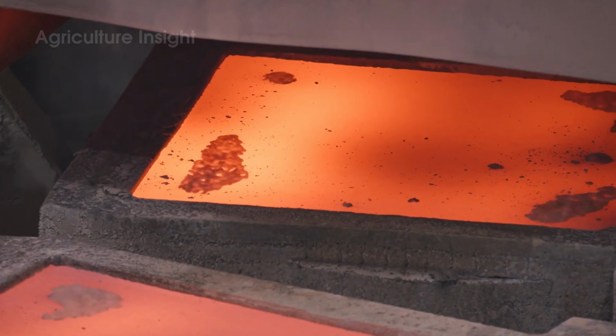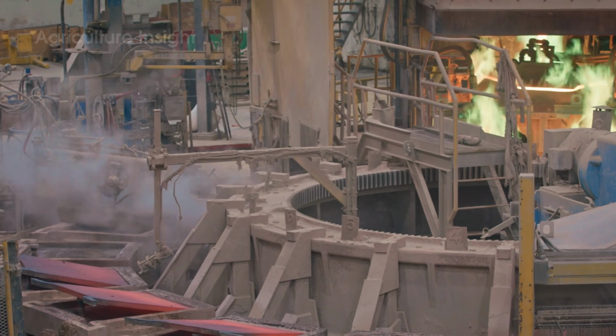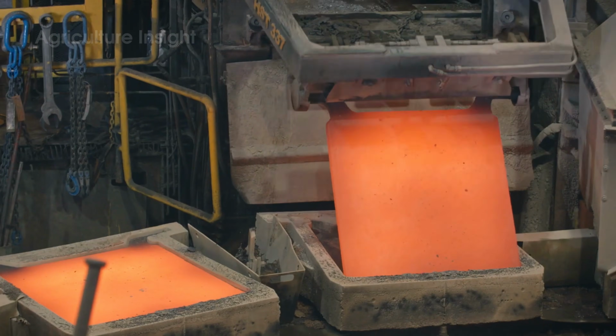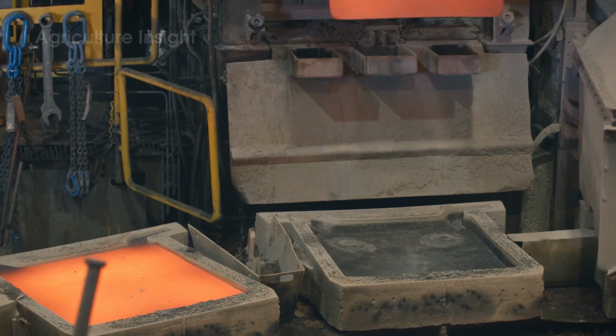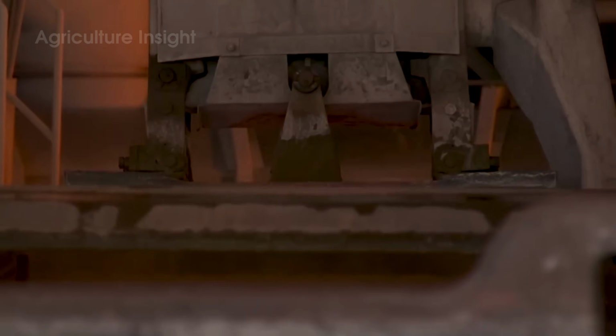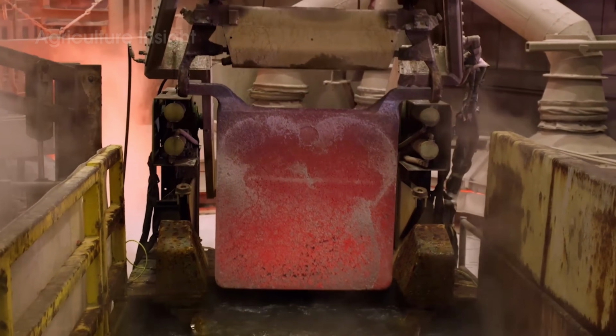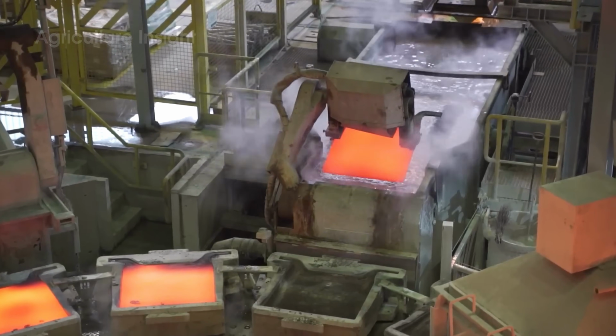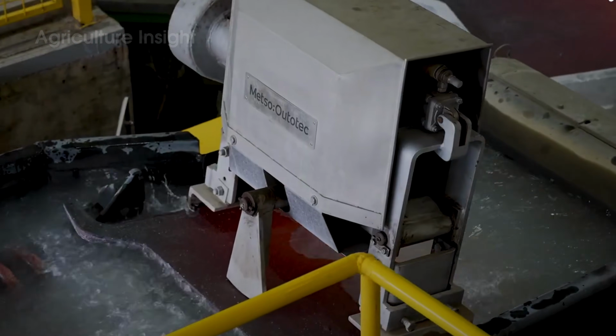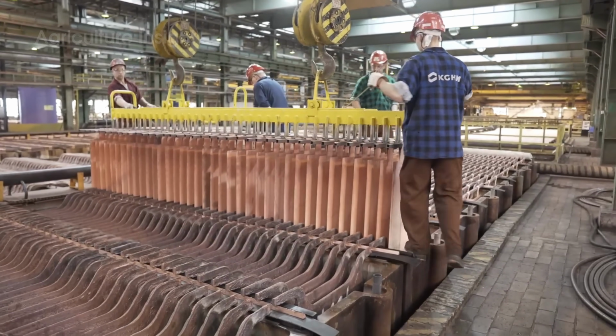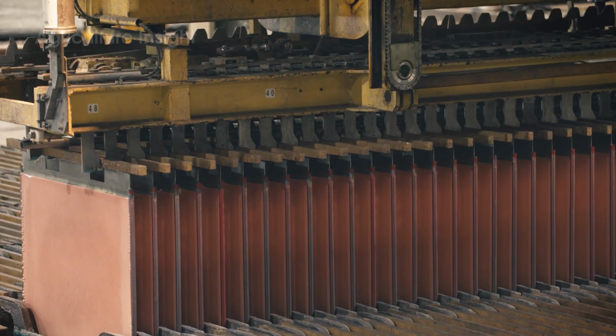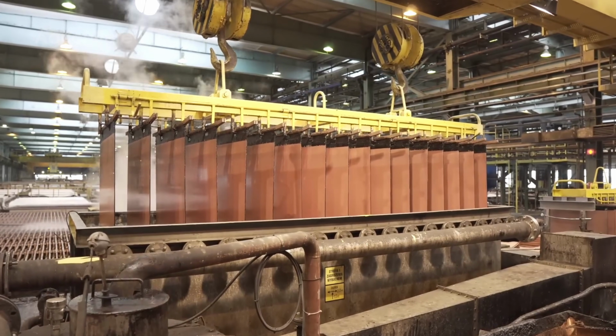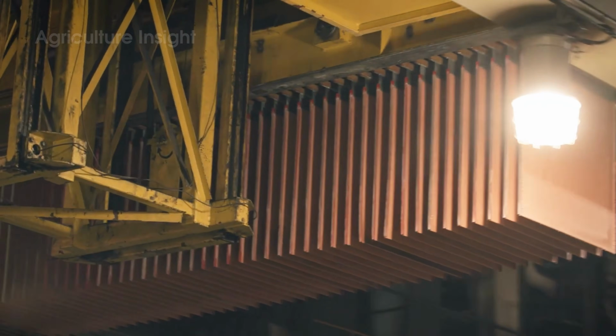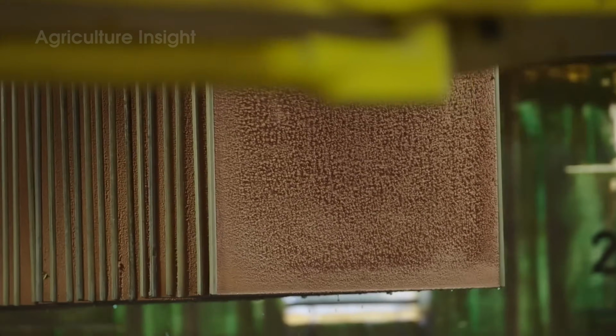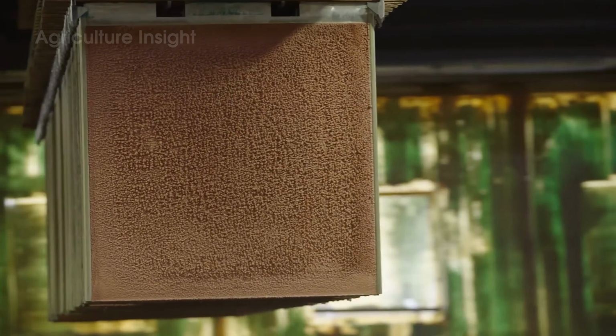The anode plates are suspended in electrolytic tanks filled with an acidic solution, alternating with cathodes made of pure metal. When an electric current is applied, copper from the anode gradually dissolves into the solution and deposits onto the cathode as pure metal, while the anode itself is consumed, its surface becoming rough, porous, and noticeably thinner over time. Insoluble impurities fall to the bottom, forming anode slime, which may even contain precious metals such as gold or silver. After several days, the cathodes are removed, now coated with copper of about 99.99% purity, ready for the next stages of processing.